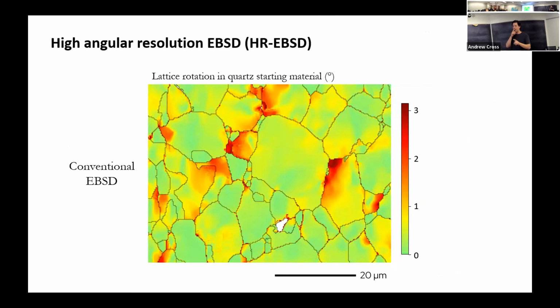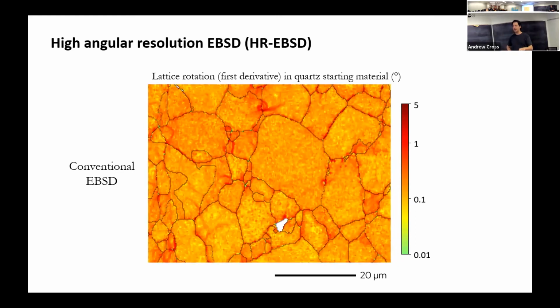We're still working on getting to that point, but what we can show is just our regular old EBSD map. Again, this is one of those misorientation maps where the hot colors indicate more bending and the green indicates regions of fairly uniform crystal orientation. We can take a first derivative of this, again just our conventional EBSD data, to pick out sites of crystal lattice bending. Anywhere you've got linear features like this, that's a localized little wall where the crystal lattice is bent on either side. With our conventional EBSD map, when we take this first derivative, we notice that it's really noisy, and we're not really able to see that much detail. Our noise floor here is about half a degree or so.